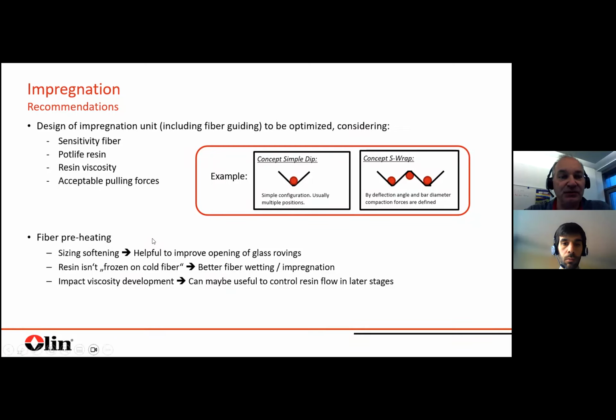Fiber preheating, it's also to be recommended. First, for softening, especially with glass, the sizing. It helps to open the glass rovings. Also, if it's preheated, the resin, let's call it, freezes not on a cold fiber. So that means if it goes into the fiber bundle, the wetting and impregnation is better. Otherwise, you have a local viscosity increase and you create a kind of micro porosity in these areas. So it's really helpful if the fiber is preheated.